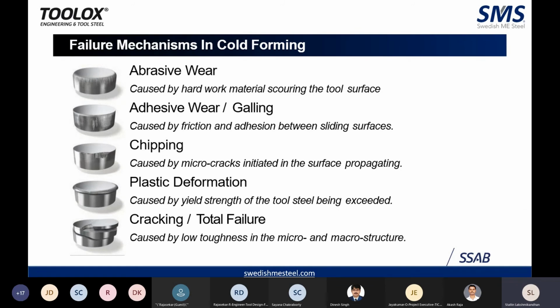The third one is chipping. This is caused mainly by micro cracks initiated in the surface propagating. Then there is plastic deformation, caused by the yield strength of the tool steel being exceeded. And cracking is caused by low toughness in the micro and the macro structure, and that also propagates into a total failure.